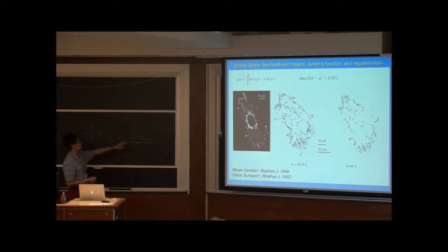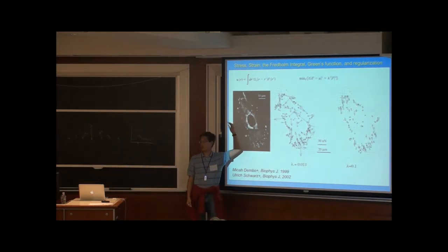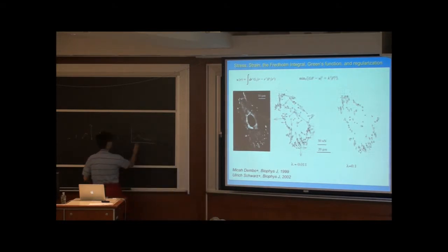If you take anything that's noisy, and that's on the right side of the integral, and now you want to reverse it, you have to do a differentiation, right? Then these small strains, these little bits of noise, get amplified, right? So let's presume that these are perfect measurements. We got this measure that now is this, right? This is the data set that I have. And let's say I presume that this was perfect data. And now I try to solve the force field.